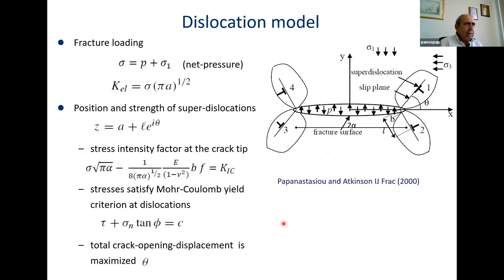And it's nice to have analytical models because in the analytical models, you can identify critical parameters. And we tried to develop an analytical model to take into account plasticity. At that time with Professor Atkinson, who retired from Imperial College now, and was always a consultant for Schlumberger, we developed this model based on the dislocation theory. With this model, we replace the distributed plasticity, you can see here, with super dislocations that are sitting in the center of gravity.